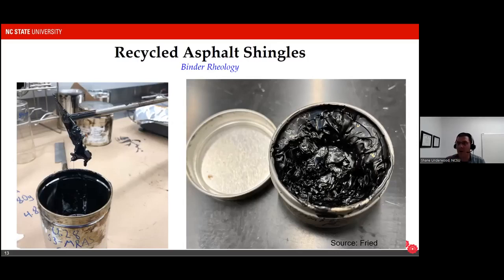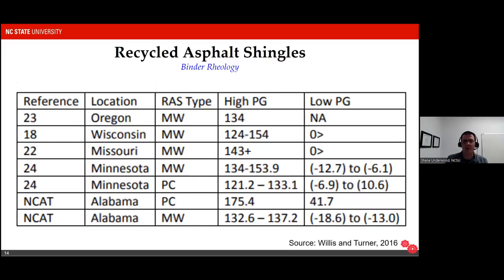There have been several studies to look at this issue. I'll show you at least one here to give you an idea. For those of you that are familiar with the USPG grading system, there have been various researchers who have tried to PG grade reclaimed asphalt shingles. And here are just some examples. So a typical high temperature grade for North America would be a PG 64 binder. And you can see these numbers are degrees Celsius. If you're not familiar with the grading system, the fact that these numbers are almost twice as large as a typical grading tells us that they are very stiff, giving PG grades up to, in some cases, 175 degrees Celsius. And this happens to be a post-consumer shingle.